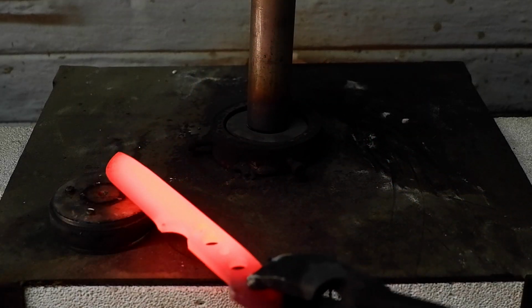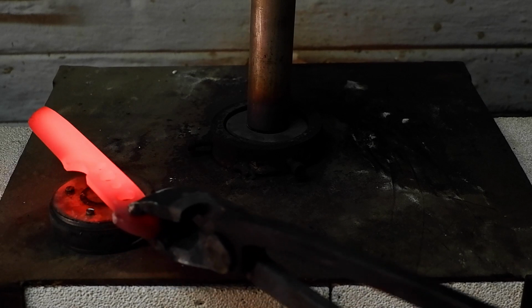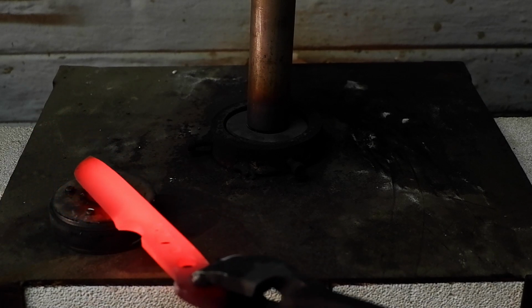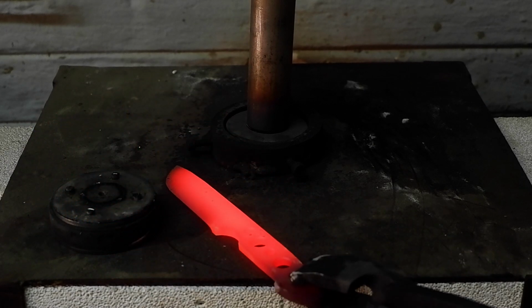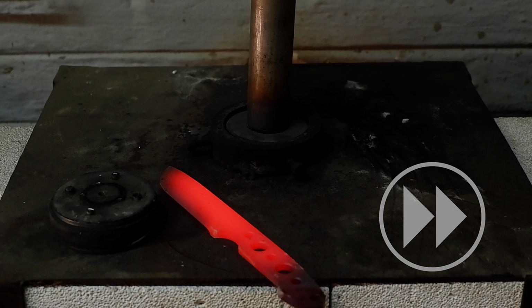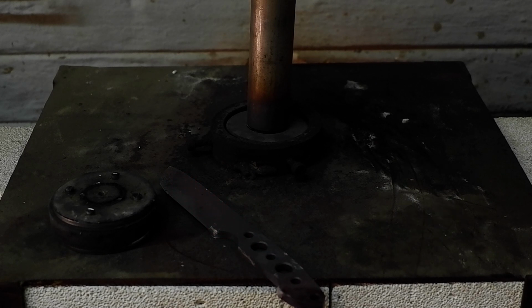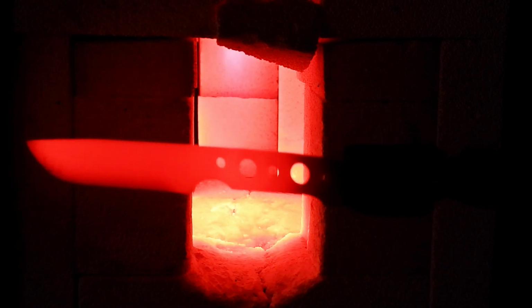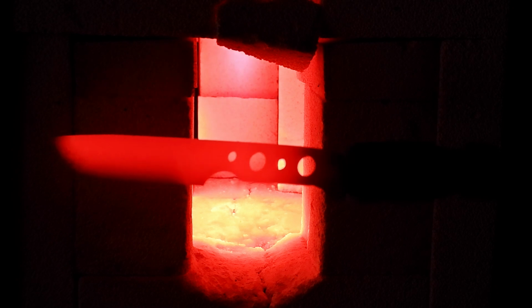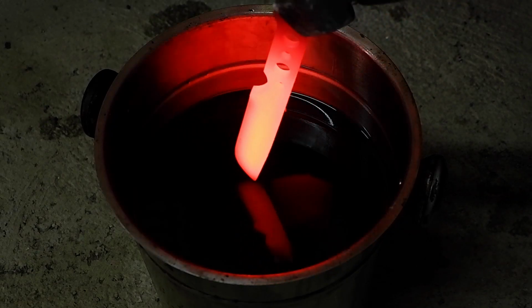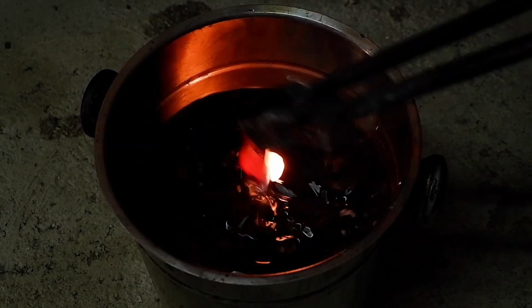Before the blade is quenched, I normalize the steel first. 5160 is a very easy and forgiving steel to heat treat. To normalize, heat it up to critical temperature and leave it to air cool until the steel doesn't glow anymore. Critical temperature is reached when the steel doesn't stick to a magnet anymore. Heat up the blade again to critical temperature, ensuring that there is a nice even heat distribution throughout the blade. Then quench in oil. I'm using a fast quenching oil specifically formulated for steel hardening.